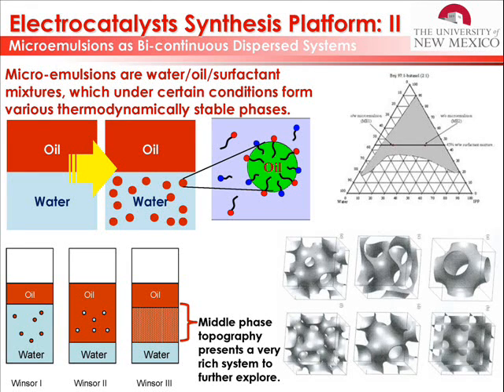So microemulsions are stabilized colloidal systems that are usually obtained on a water-oil interface when the surface tension goes down to 0. And the way to get the surface tension down to almost 0 is when you have a mix of 2 soaps. One surfactant is predominantly soluble in water, so it has a critical micelle concentration in water, and the other surfactant is predominantly soluble in the oil phase. So it has a CMC in the oil phase.